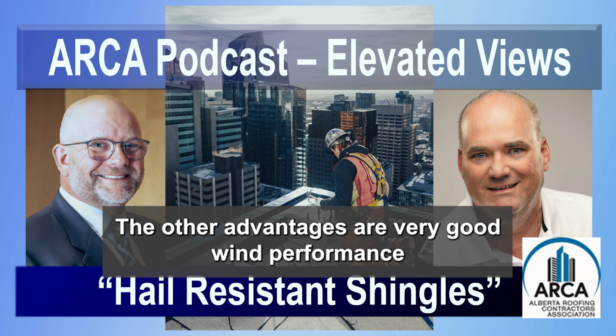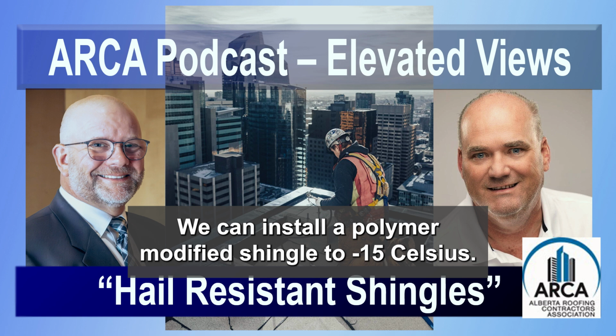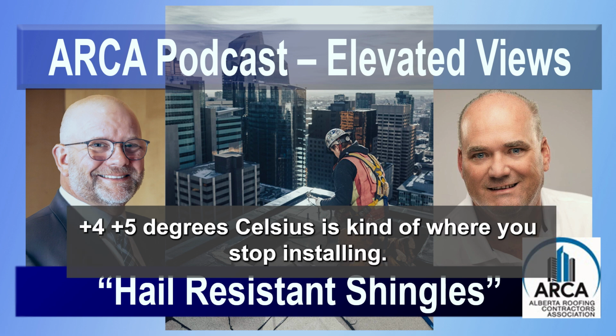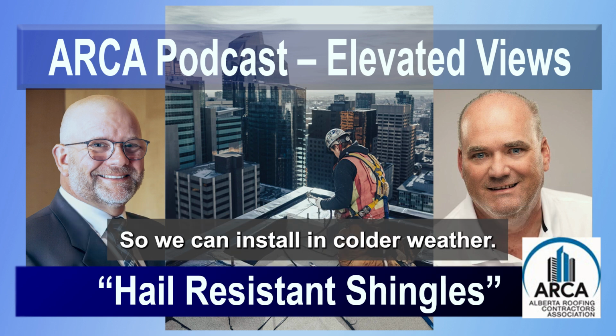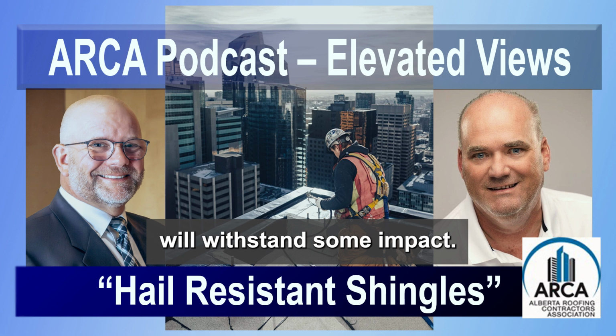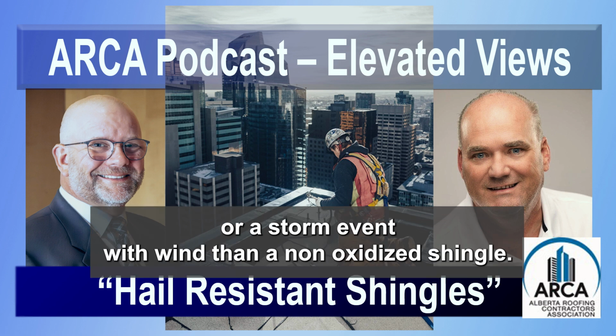The other advantages are very good wind performance, because the shingle doesn't get as brittle in the cold. We can install a polymer-modified shingle to minus 15 Celsius. Most other shingles, or most oxidized shingles, plus 4, plus 5 degrees Celsius is kind of where you stop installing. So we can install in colder weather. And one of the reasons I'm probably sitting here is that a polymer-modified shingle will withstand some impact. So it will perform better in a hail event or a storm event with wind than a non-polymer-modified shingle.